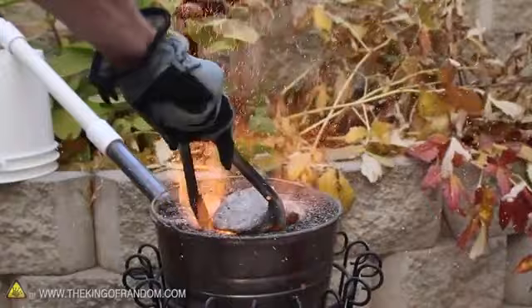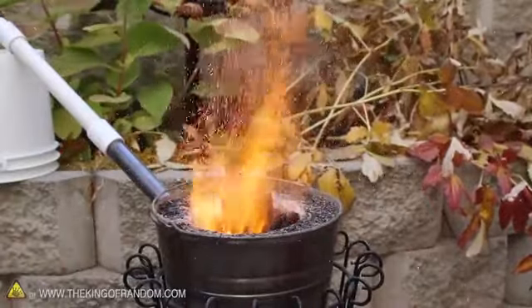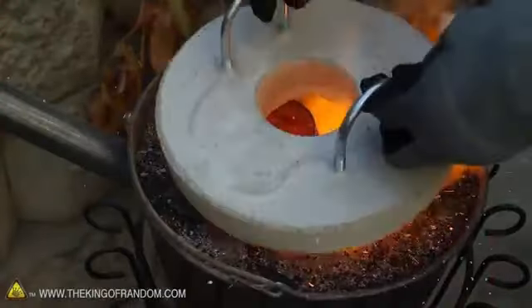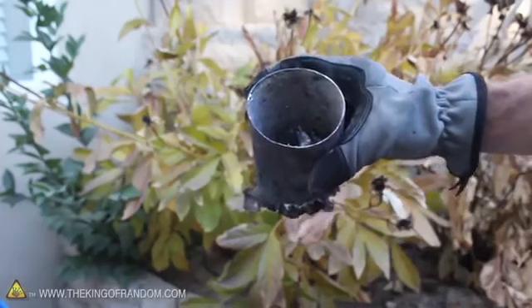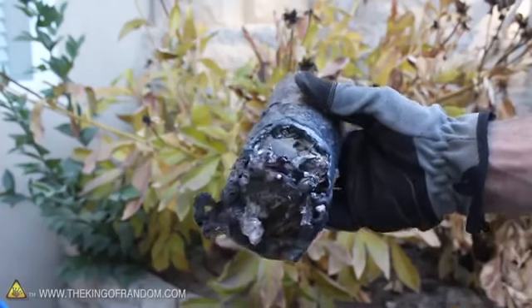The first thing I noticed about lump charcoal is it emits a shower of sparks, so you definitely want to make sure you're wearing long sleeves or you're going to end up with little sparks burning your arms. The other thing is it burns a lot hotter. In the early days I had one of my steel fire extinguisher crucibles in there, and it actually got so hot that it melted the steel and all the aluminum leaked out. So if you use lump charcoal, it'll burn a lot hotter. It's very, very powerful stuff, but you need to watch it more carefully.